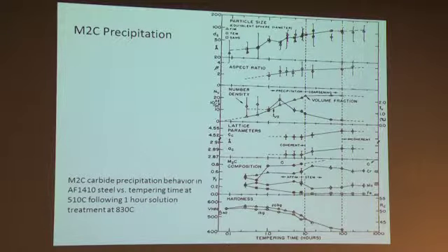This enabled a parametric approach to the design of precipitation-strengthening efficiency in these steels, and with those methods we've been able to design steels that for a given carbon content are 50% stronger than previous steels.